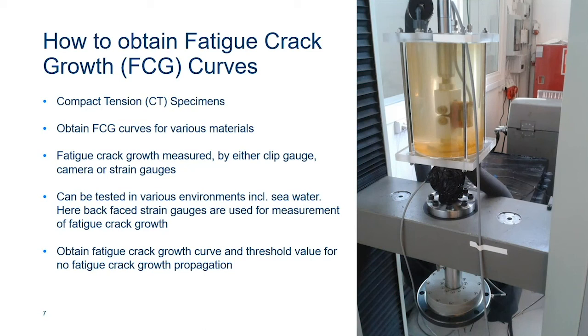So how do we do these fatigue crack growth curves? Well, first, you make a start notch in the specimen, and you do a fatigue pre-crack where you actually lower the stress intensity at the crack tip, so you get a very, very sharp crack tip. After that, you can do the threshold test, which is quite similar to the pre-crack, but you start with a very sharp crack, and then you can find the threshold value for where the fatigue crack growth actually stops, where lower values will not generate any fatigue crack growth. After that test, you can do the constant load test, or the stress intensity increasing test method,